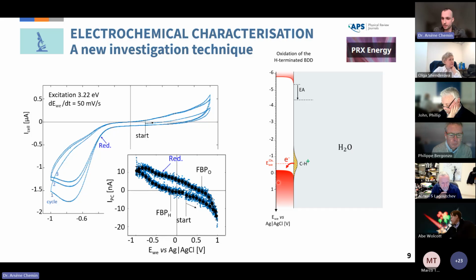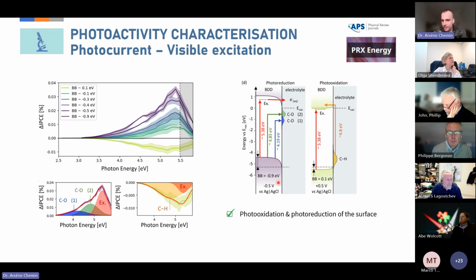And if you put the numbers together, you find out that it is almost, if not always, systematically the case every time you put diamond in water. So this is why hydrogen terminated surfaces are not stable in a liquid environment or in air. It's because the chemical potential of the liquid environment is enough to drive the oxidation of the surface. One other thing that we were able to demonstrate is that light can also trigger some photoreaction and some electrochemical reaction at the surface. So we can also photo-oxidize and photo-reduce the diamond surface.